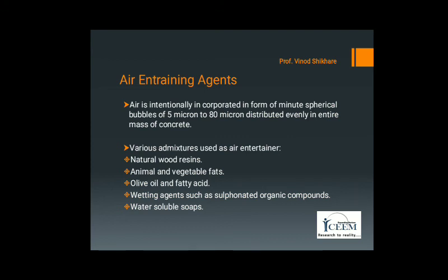The other admixtures used in conjunction with air entraining agent will also significantly affect the amount of air entrained. The use of fly ash in concrete will reduce the amount of air entrained. Similarly, the use of calcium chloride also has the tendency to reduce and limit air entrainment.